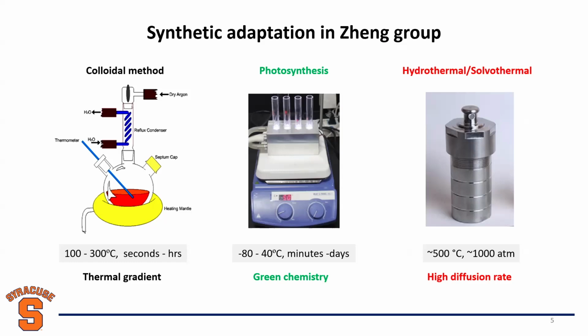Okay. We're also interested in some reactions under extreme conditions, like high temperature and high pressure. If we use water as the solvent, this is called a hydrothermal reaction. If we react in an organic solvent, it's called a solvothermal reaction. You can go to pressures up to like 1,000 atmospheres. Because of the high ion diffusion rate under those extreme conditions, we can achieve some unusual phase structures of nanomaterials, which are usually not easily obtained under ambient conditions.